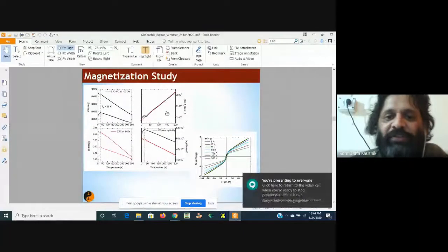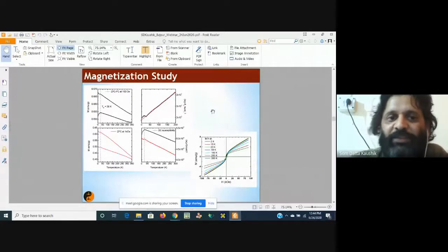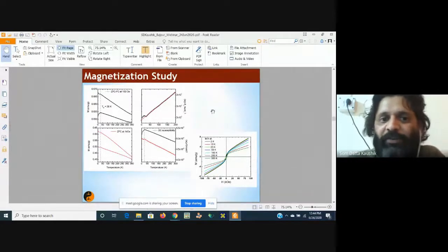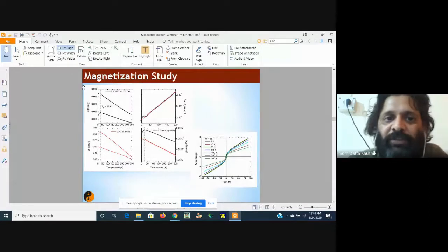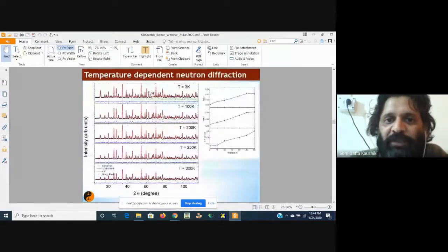So we should have an idea about the magnetic transition temperature. For this particular compound, it is around 26 Kelvin. So we can study the neutron diffraction at low temperature. This is the pattern at 300 Kelvin, and this is at 3 Kelvin.